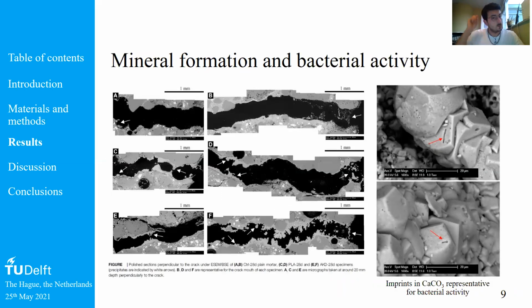What we also did was evaluating the mineral formation and bacterial activity through SEM analysis. So we made sections perpendicular to the crack, and you can see some pictures about it on the left side of the screen. And you see that in the first row you have control specimens. Well, the sections related to the control series, and you see that actually the amount of precipitate is very limited. This is indicated by the white arrows.